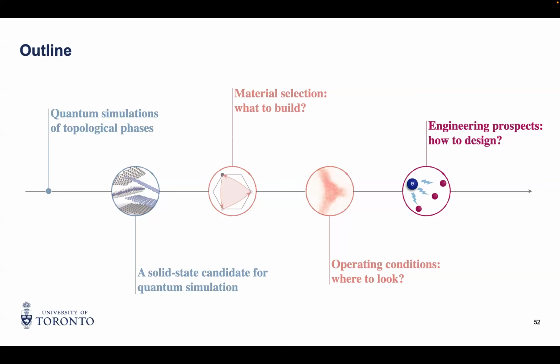Right, this is very hard because then you're asking a quantitative question that is global, and I think it's just hard. We've tried. We have a proxy for what would be the magic angle for all of these materials. And if the magic angle that you predict, the angle at which the band becomes extremely flat, is above the relaxation angle, then you can trust it. It turns out that most of the time it's not in the good direction. So we don't have a good answer yet.